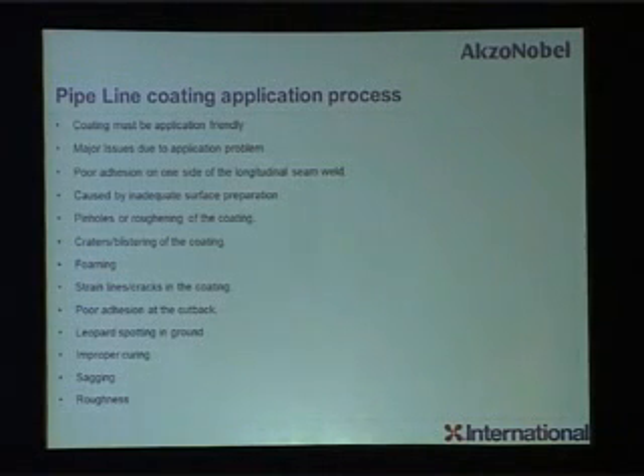What are the issues? Like if they are not mixing properly, when you go to the pipeline site, nowadays all pipeline coatings are applied through plural component guns, right? So base is going, curing agent is going. Now if it is not mixing properly through the spiral, and it is depositing into the pipe, in the pipeline, what will happen is after a certain time it will be cured, 90% somewhere, 100% somewhere else, with excess curing agent elsewhere. So all those things we must emphasize, we must highlight during the meeting between applicator and manufacturer.